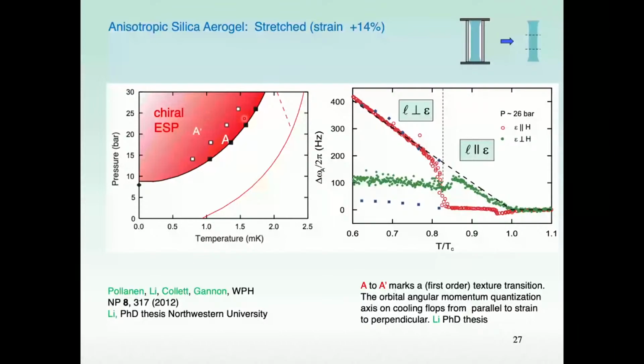The distinction between these two regions of A phase is the following, and it's shown in terms of frequency shifts, which I've said before is a measure of the order parameter amplitude as a function of temperature. And depending on the orientation of the angular momentum with respect to the anisotropy axis imposed on this aerogel by stretching, the frequency shifts show a sharp change, and that sharp change at a given temperature is where these open squares are delineated. The orientation of the angular momentum relative to the anisotropy axis is parallel in this region and perpendicular over here on the left. So what has happened is the angular momentum decides to flop from being parallel to the anisotropy axis to perpendicular to it at a well-defined temperature. Let's call that temperature Tx.